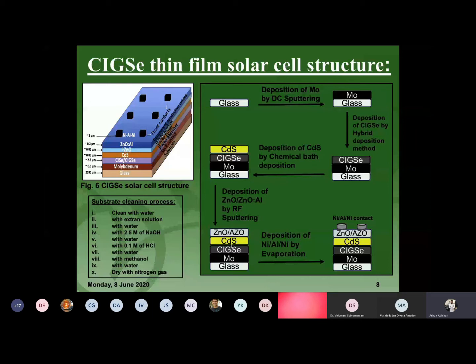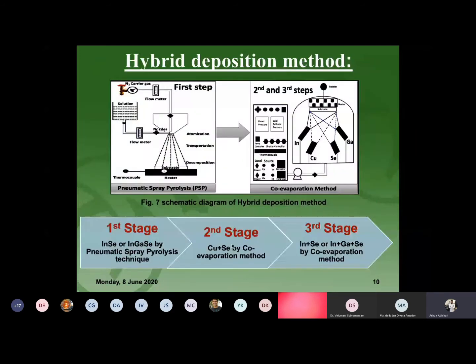Figure 7 shows the hybrid deposition method that I am working on. The proposed hybrid deposition method resembles the 3-stage co-evaporation process. It combines non-vacuum pneumatic spray pyrolysis and vacuum co-evaporation method in order to reduce the cost by using a low-cost technique and less pure precursor material.